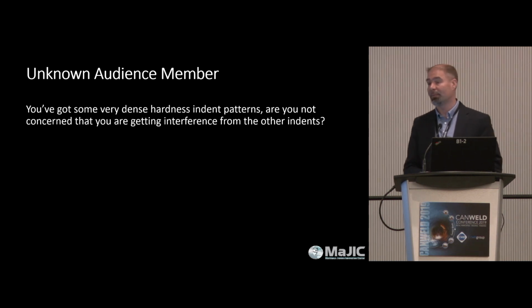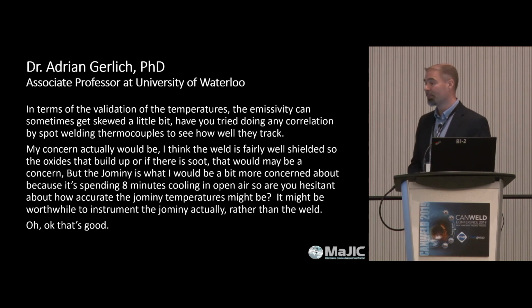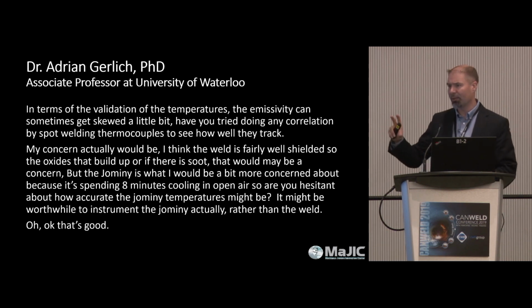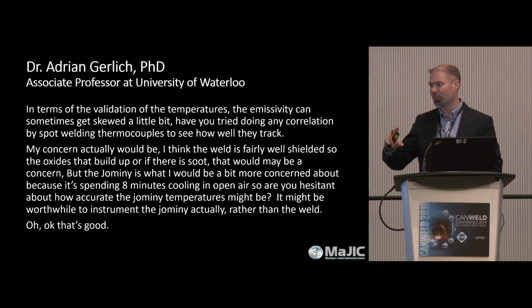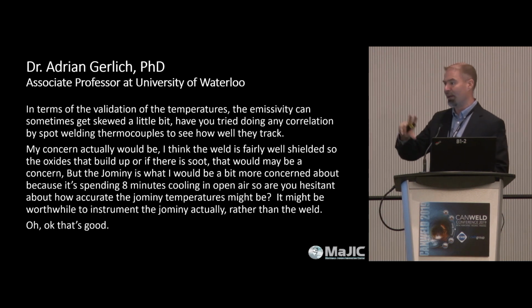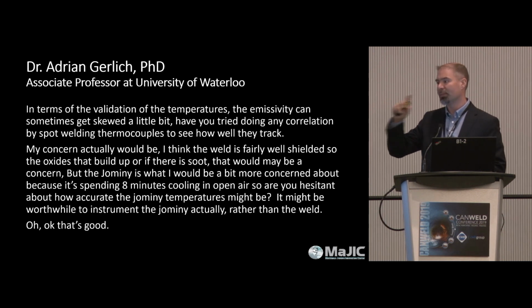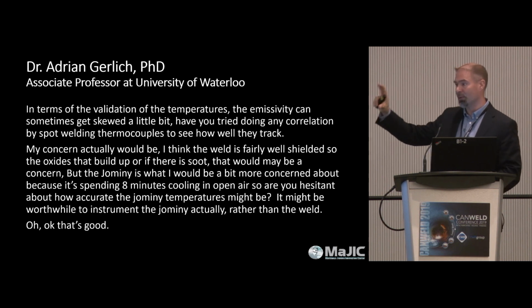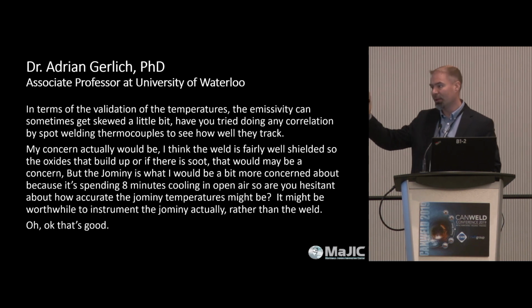Adrian? So in terms of the validation of the temperatures, the emissivity can sometimes get skewed a little bit. Have you tried doing any kind of correlation with spot welding thermocouples to see how well they track? Not yet. The emissivity issue comes into play with, right now, we're assuming that it's working itself out with the Jominy end quench. Because we're looking at an actual measurement on the Jominy, and we're correlating that, so we're hoping that it doesn't matter.